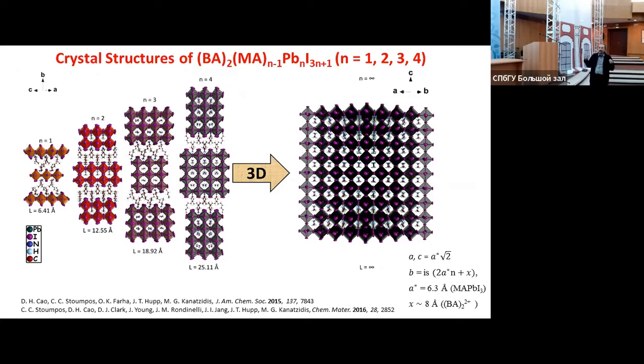And you can actually predict what you expect to see by this kind of reaction, because you know that the dimensions of the unit cell should stay exactly the same, and the only thing that changes is this spacer, the molecular scissors that you use to separate the layers. And butyl ammonium is an effective one, the most well-studied so far. And we know exactly, we can predict actually the size of the unit cell.